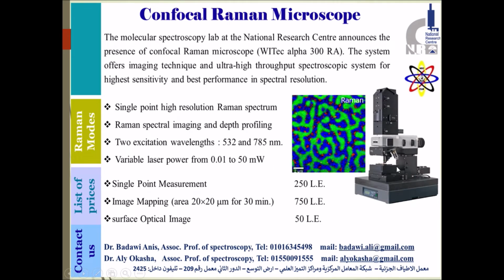In our lab we have this nice instrument, which is the WITec alpha 300 RA, from German technology. Using this instrument we can measure a single point spectrum with high resolution. Also we can measure Raman spectral imaging for the surface of a specific sample, and we can also perform depth profiling. With our microscope we have two excitation wavelengths, 532 and 785 nanometer. We can change the laser power from 10 microwatt to 50 milliwatt.